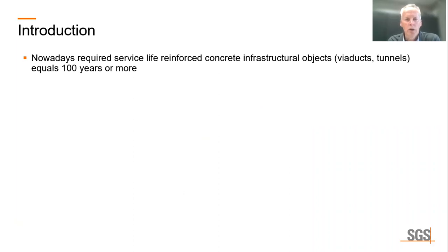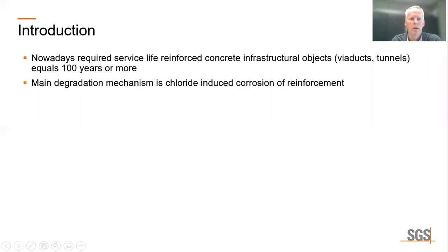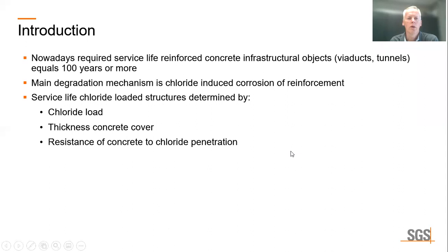Nowadays, the required service life of reinforced concrete infrastructural objects like viaducts and tunnels equals 100 years or more. The main degradation mechanism of these structures is chloride-induced corrosion of the reinforcement. The service life of such chloride-loaded structures is determined by the chloride load, the thickness of the concrete cover, and the resistance of the concrete to chloride penetration.